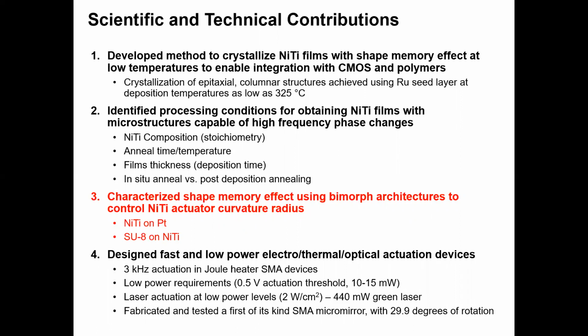In the second case, I spin coated SU8 on top of NiTi to achieve a similar effect. In this case, the CTE of SU8 is very large compared to NiTi, so therefore it makes up the top layer. When processed at high temperatures, the contraction of the SU8 on top of the NiTi causes the bilayer to curl upwards when released from the substrate.